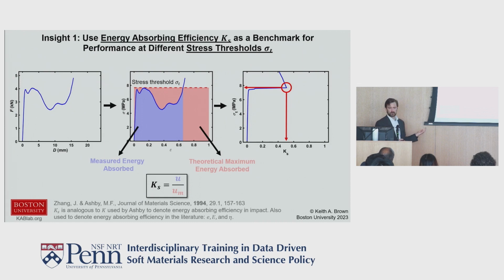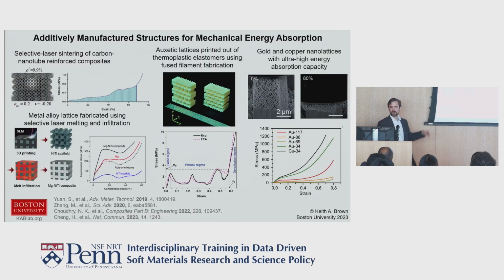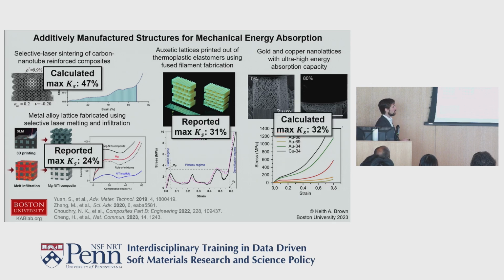And so with this new lens, we said, okay, we'll see how people do in terms of this efficiency. So we turn back to the slide I showed you earlier. These are the mechanical structures I mentioned. Again, these are all 3D printed structures designed for energy absorption. And if we compute their Ks values, their efficiencies, they tend to range from about 20% to just below 50%. That includes a presumably world record holding structure in terms of mass efficiency. It was only 30% efficient by this metric. So we think there's probably a lot of room to grow on this.